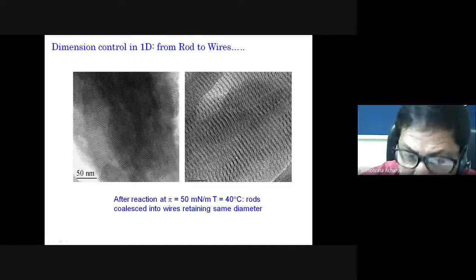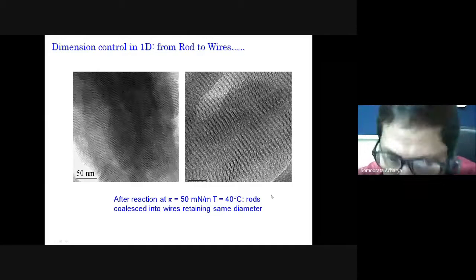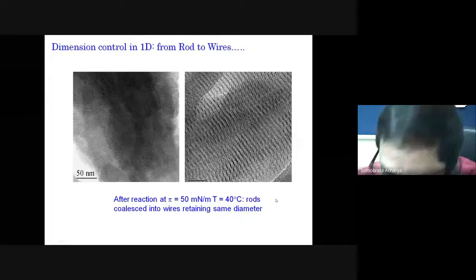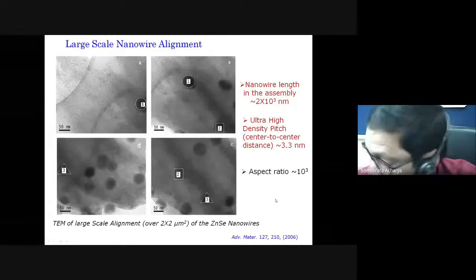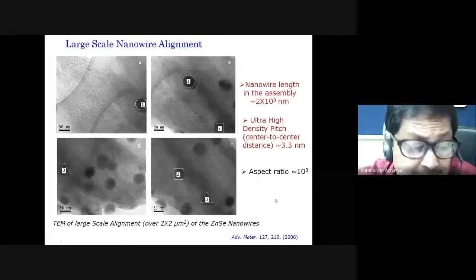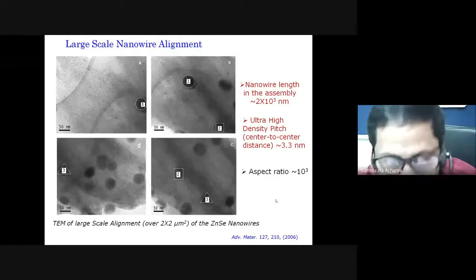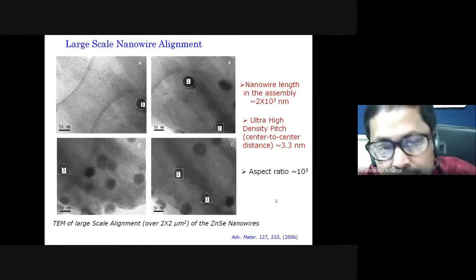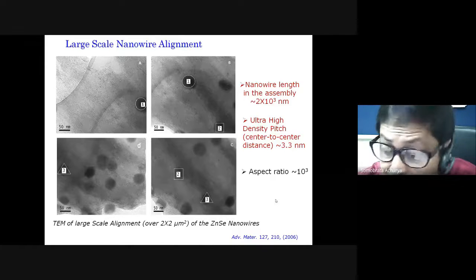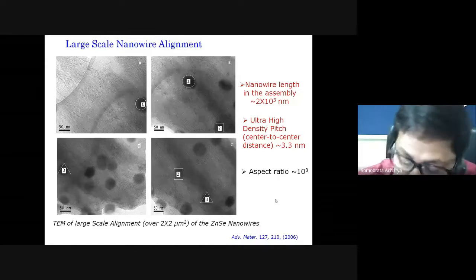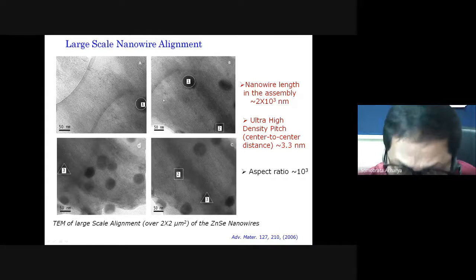same diameter. So this is something like you are doing some kind of chemical reaction and giving some amount of heat energy, which is just above the ambient temperature, 40 degrees Celsius, and eventually you can convert these nanorods into nanowires retaining the same diameter there. So if it works for the nanorod to nanowire conversion, it should also work for the nanowire to other kind of nanosheet formation also. So that also has been tested.